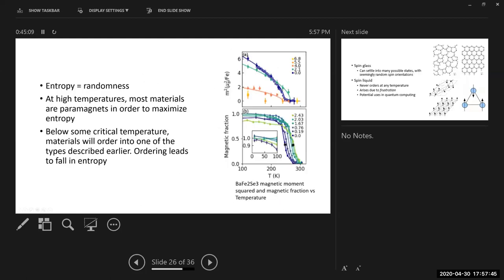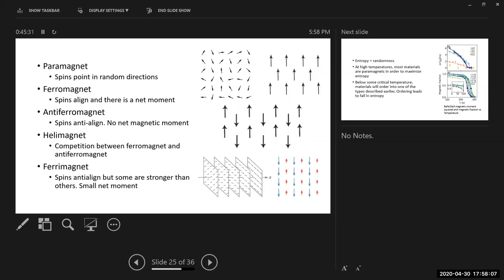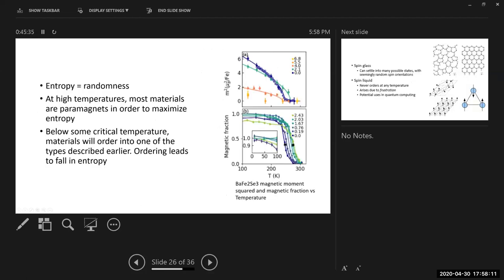And this is the fraction of the material that is an anti-ferromagnet. And you can see that there's a temperature above which it's just zero, above which it's a paramagnet. But below that temperature, all of a sudden, the whole material is antiferromagnetic. All of a sudden, the moment is huge. So this is what we call a phase transition. Going from this state of high entropy, then decreasing the temperature, and all of a sudden going into the state of lower entropy, going from a paramagnet to an antiferromagnet.